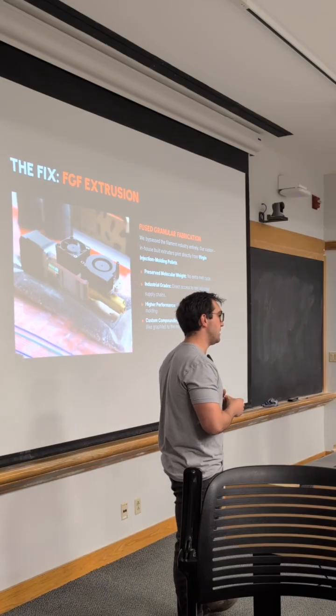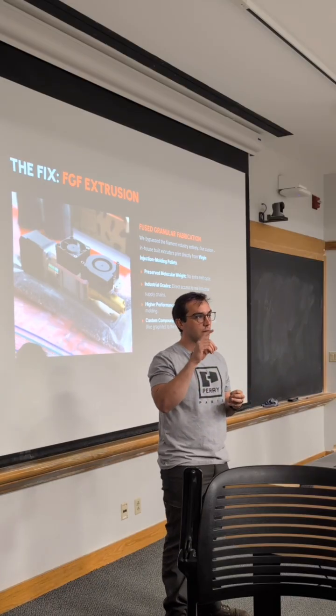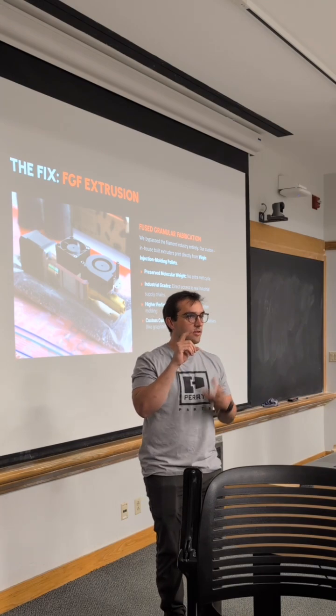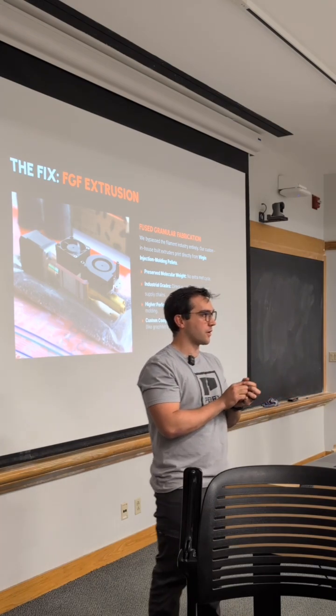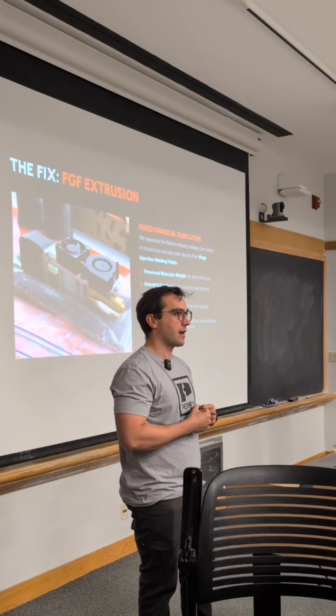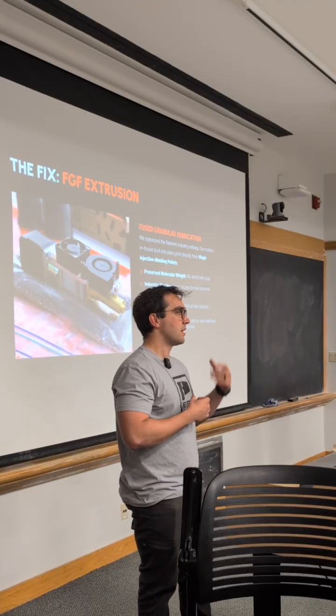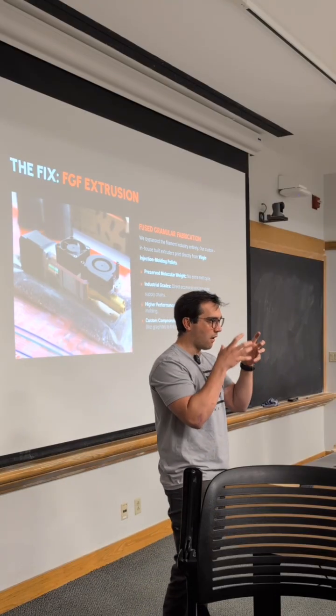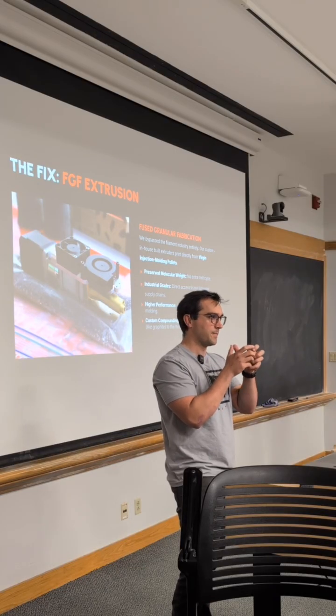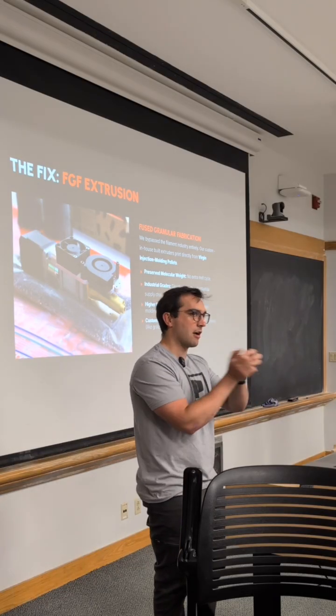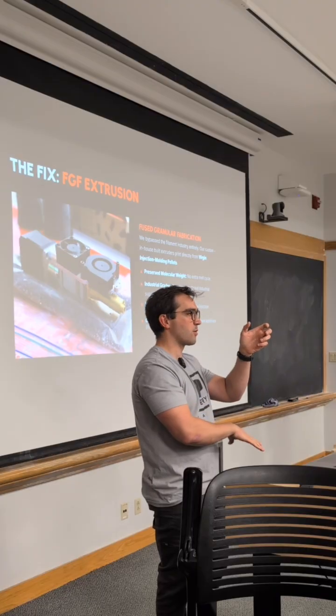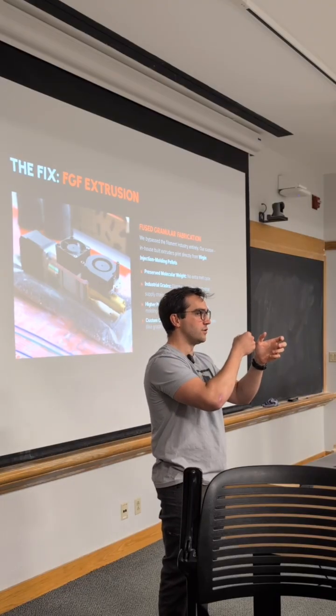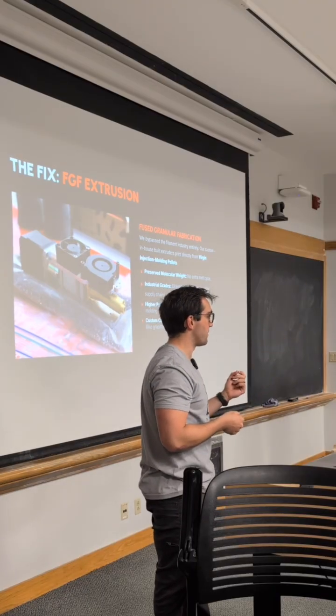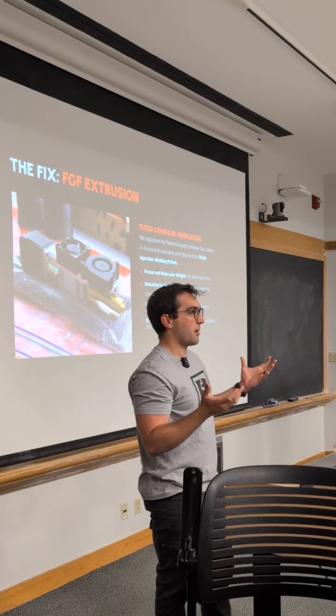And so we machine in-house a little micro injection molding screw as well as a barrel. And those parts interface with each other to grind, compress, and then extrude injection molding pellets right on our 3D printer's print head. So this whole thing is reciprocating around in the XY plane, the Z-axis is moving down, and we've got a large feed tube coming down with all the pellets in it. This checks a lot of boxes for us.